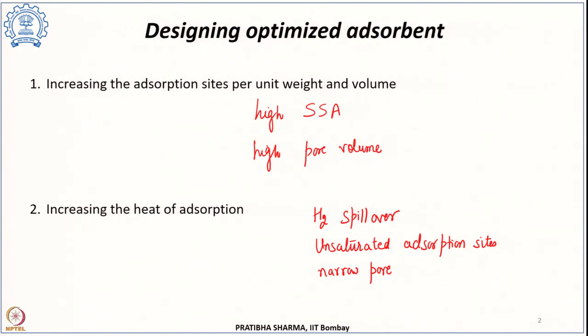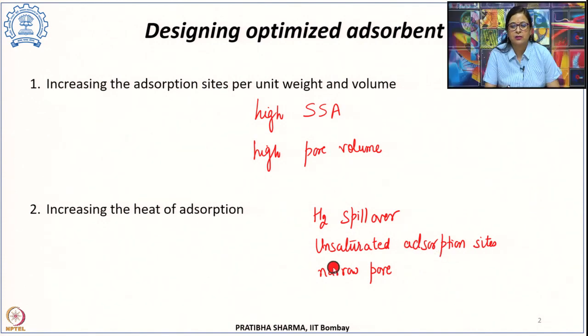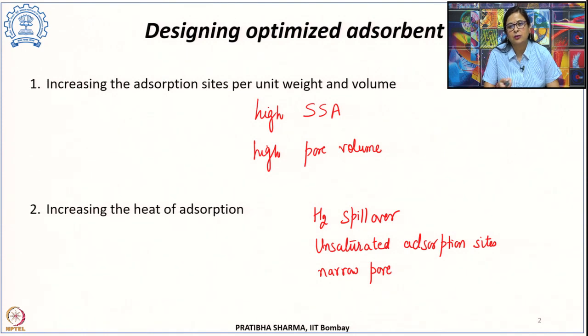For the hydrogen spillover effect, transition metals like platinum or palladium have been introduced inside the host matrix, but this has not shown much promising results. Including unsaturated adsorption sites by changing the chemical composition of the porous host material — introducing certain species including metals — was also not very helpful. The interaction of the hydrogen molecule with the functionalized adsorption sites was not very strong, and the heavy metals introduced in fact reduced the gravimetric capacity.